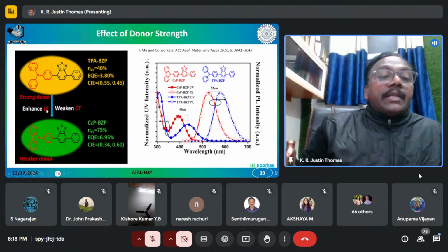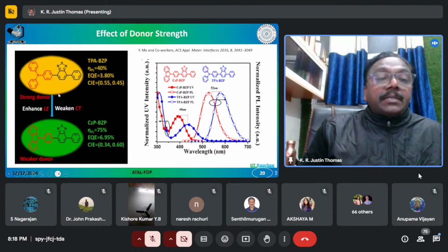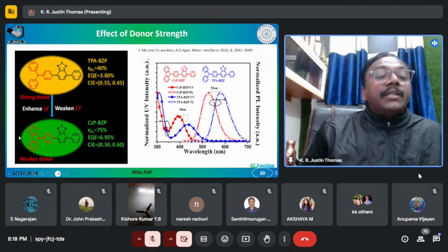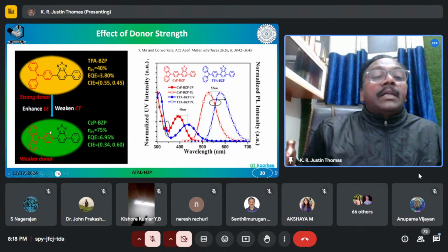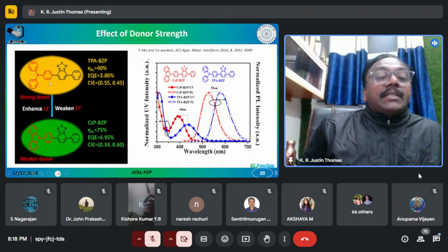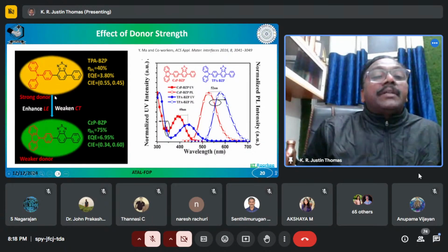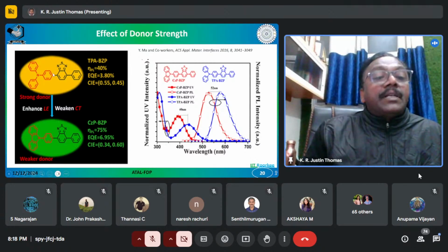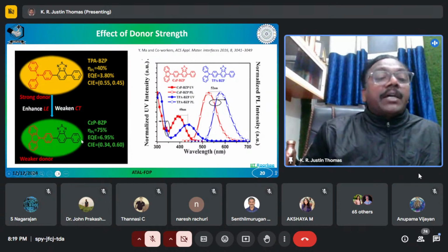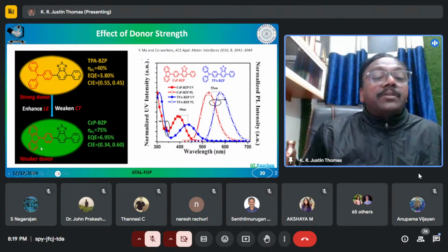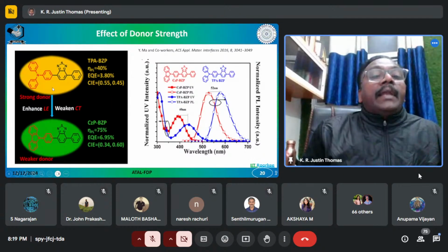If you look at the two molecules that I have shown here, both have benzothiazole as an acceptor, and one molecule has triphenylamine as a donor, which is a strong donor, and the other has a weaker donor, carbazole. The donor strength difference makes a huge difference in the emission characteristics. Here there is a strong charge transfer. Here there is a weak charge transfer. So now what you have here is a balance between charge transfer and local excitation in this molecule, and that manifests in the emission characteristics also.